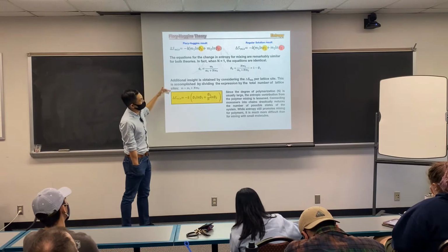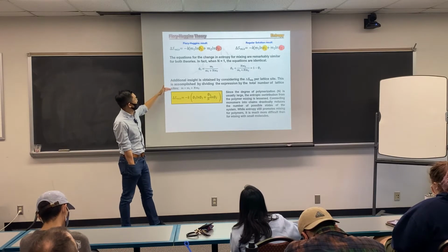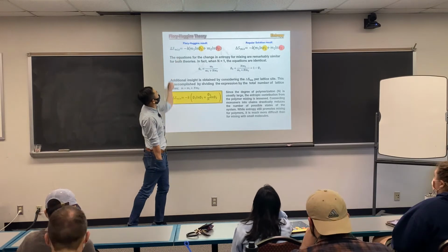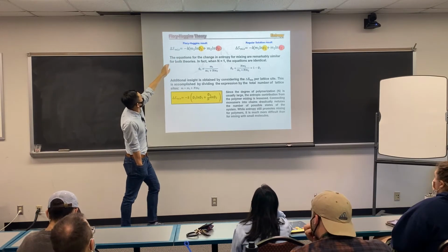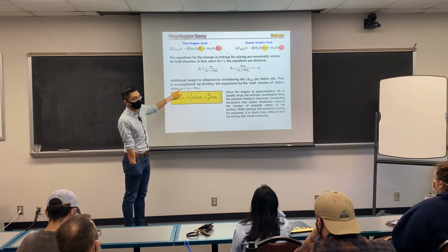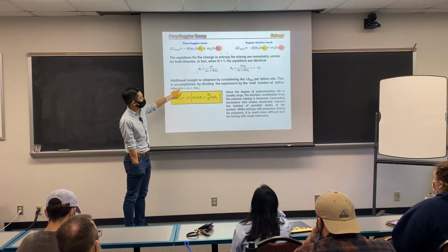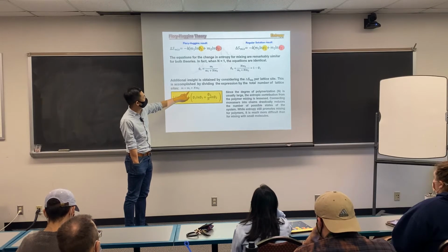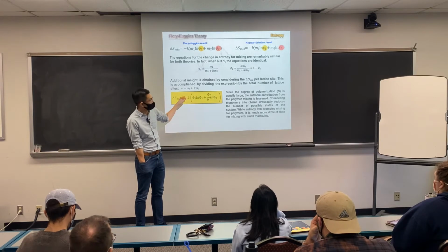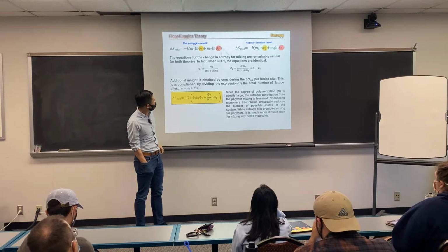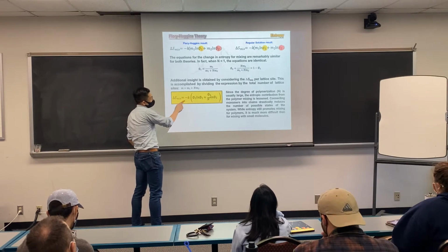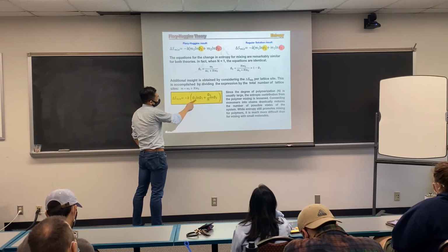a total system, but we have normalized per lattice site, which means we need to divide everything by n, using this equation. If this is divided by n, the total lattice sites, again, n is defined by how many solvents, how many polymers, multiplied by degree of polymerization. We will reach this conclusion. Per site, delta S mixing will be equal to minus k phi 1 log phi 1.